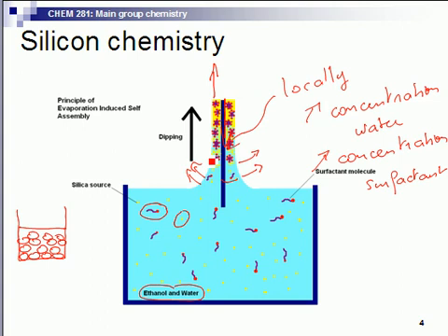At the same time, the concentration of water increases, which means that you have water that starts attacking your tetraethoxysilane to produce silica. So, tetraethoxysilane is soluble, but silica is a solid, so you start polymerizing silica around your micelles.